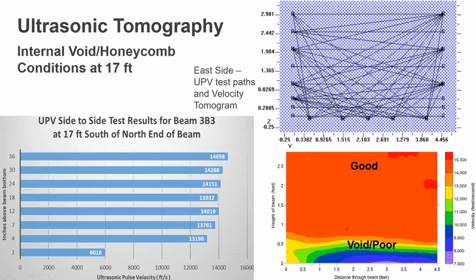So with all this data, you can see we're getting very good coverage with a lot of crossing ray paths, direct and angled in the bottom portion of the beam, less so in the upper portion where it was better conditioned. You didn't have any access to the top, so we could not get as much. If you've just got a straight across measurement, it's going to be the normal UPV average result. So if you looked at what we got from the straight across measurements at every 6 inches, going from 1 inch up to 36 inches, you can see the bottom at 1 inch is 6,000 feet per second. It's much faster at 4 inches up, 13,200, but then it gets progressively faster until when you get to the very top, it's the fastest velocity, very good quality concrete.